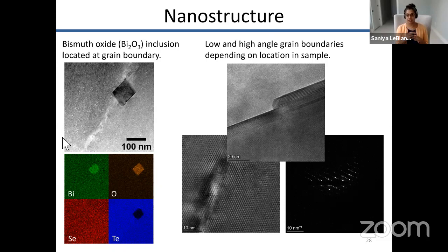And then we also, from the ability to characterize the nanostructure, get to see some really interesting results of what's happening at the nanoscale in the material, particularly, for example, at the grain boundaries. And so the way the lattice transitions across grain boundaries is going to impact the carrier transport, the phonons and electrons through that material, which means it's going to impact the thermoelectric properties.